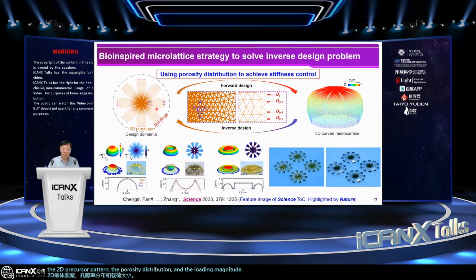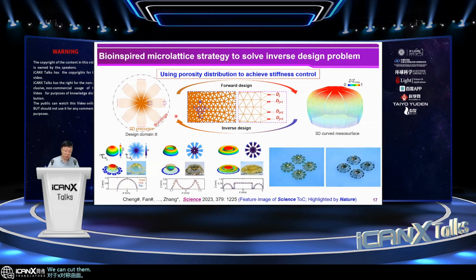And in particular, for axisymmetric surfaces, we can cut the surface into a set of interconnected 3D ribbons. And for each 3D ribbon, we can derive analytical solutions to the width distribution and the porosity distribution. And here are a few examples of the inverse design for the hemisphere, volcano-like surface, and palace-like surface. And for each structure, this is the design target.